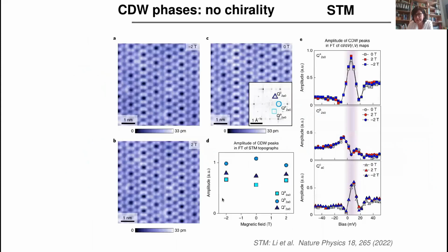However, more recently, using the same samples, as far as I know, these are the same samples as in the previous work, STM data from Ilija Zeljkovic also go into this charge density wave phase and apply a magnetic field. Let me show you these results: this is the amplitude of these charge density wave peaks, we have three of them, and by just changing the direction of the magnetic field, basically they don't observe anything special.